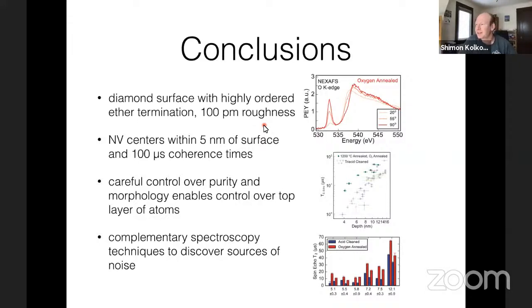So why is it harder to make good diamond surfaces? What surfaces are easy and why? Yeah, so there are three problems with diamond. One is that it's very inert. So a lot of chemistry that you would like to do, like wet chemistry, doesn't really work on diamond. To give you a contrast, for something like silicon, it's relatively easy to control the termination because there exist methods where you can oxidize the surface and then remove it. And there is no such chemistry for diamond.